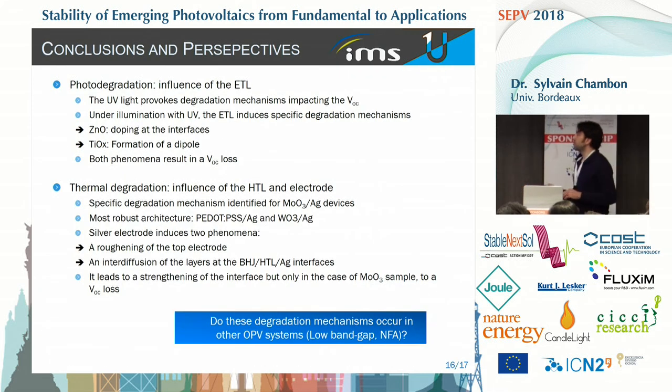So in conclusion, for these two studies, the photodegradation and the influence of the ETL, we managed to identify two degradation mechanisms, which depend on the ETL used. In the case of titanium oxide samples, we observed the formation of a dipole. And in the case of zinc oxide, we observed some degradation at the interface with the active layer. And in the case of the thermal degradation, we identified a specific degradation in the case of molybdenum oxide-based samples with silver.